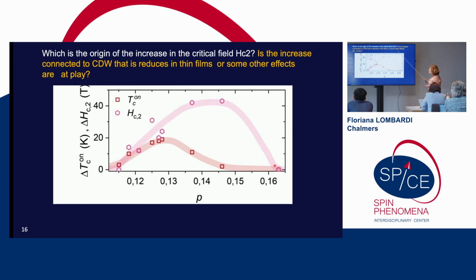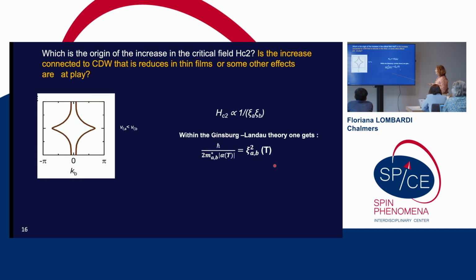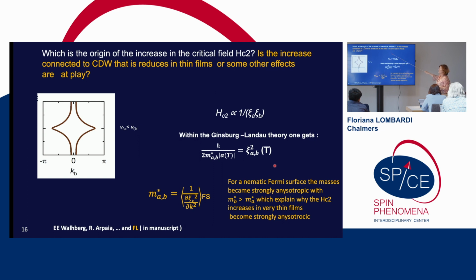But then why do we get this? And the reason we believe is that the surface is nematic. So we have these tips here. The HC2 is inversely proportional to the product of the Xi. But within the Ginzburg-Landau formalism, the Xi is inversely proportional to the mass. So here you have that the bands are flatter, so you have a higher mass, and this higher mass gives lower Xi, and then you get a higher HC2. So this is a consequence of this peculiar Fermi surface that we are exploring in our films.